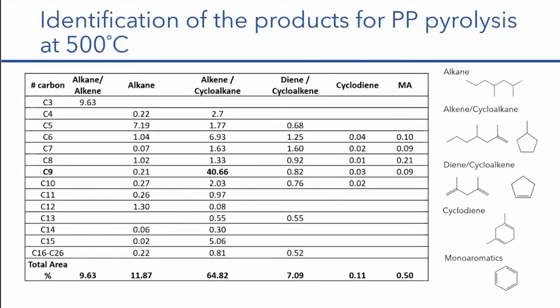So for the identification of the products, we have identified almost all these 300 products, which is a lot. And we have grouped them by carbon number and by the type of hydrocarbon. So we identified alkanes, alkenes, and cycloalkanes, which is very important because it's not widely reported for the analysis of PP. In the publications, they are using just one-dimensional gas chromatography, so they are not able to separate them. Cyclodienes, and also a small amount of monoaromatics.